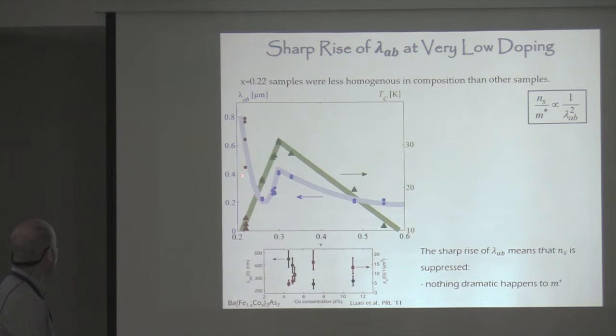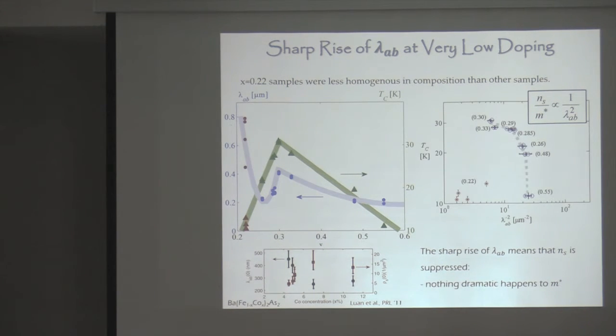So this overall behavior is more reminiscent of other measurements in other pnictides where lambda shoots up as you get to the edge of the dome, and that kind of makes sense because there is a competing phase there, and it's taking charge carriers away from the condensate, and so the penetration depth diverges or goes up because of this relationship. If you add these points to the Uemura plot, you see that they are really different from the more highly doped samples.